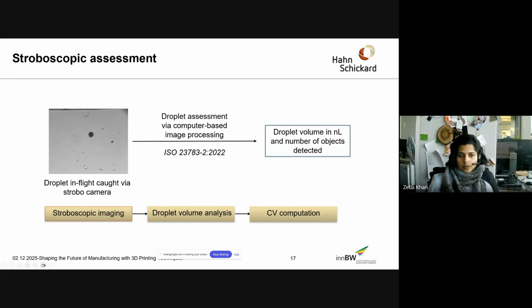We capture images of the molten metal droplets. So this you see in the black. In the center here is the molten metal droplet. Each droplet can be captured with our camera, and then we process it using an ISO standard technique, which was also developed here at Hahn Schickard. And we finally do some computation for the droplet volume and number of droplets.